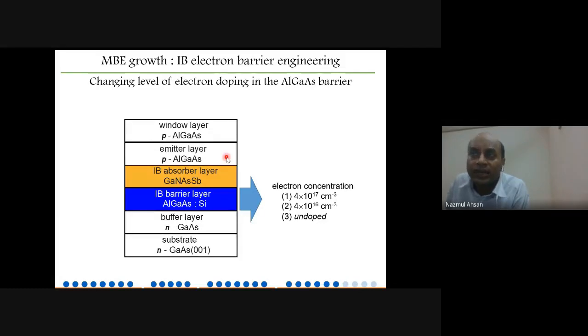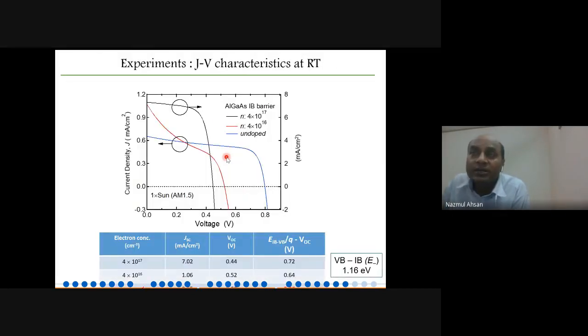This is how we are designing our gallium nitride arsenide antimonide. And this is the real semiconductor, a real solar cell. If you have a high doping in your barrier, the red and black one being the high doping barrier, then you have a very low open circuit voltage. But if you reduce the doping concentration, you are increasing the open circuit voltage, and you gain more voltage if you have the least amount of doping in your barrier.